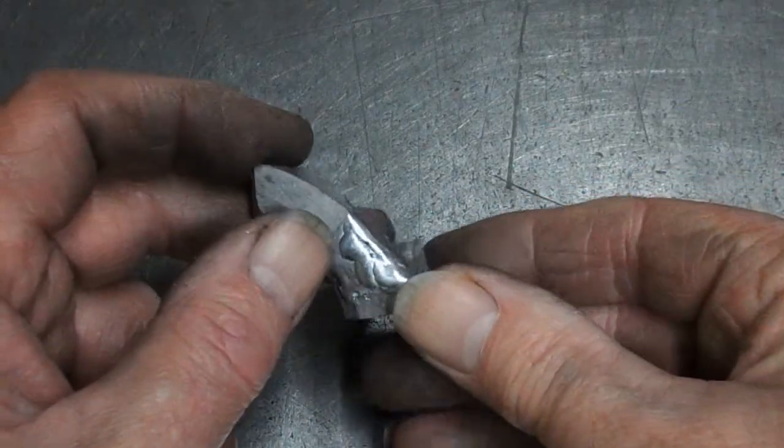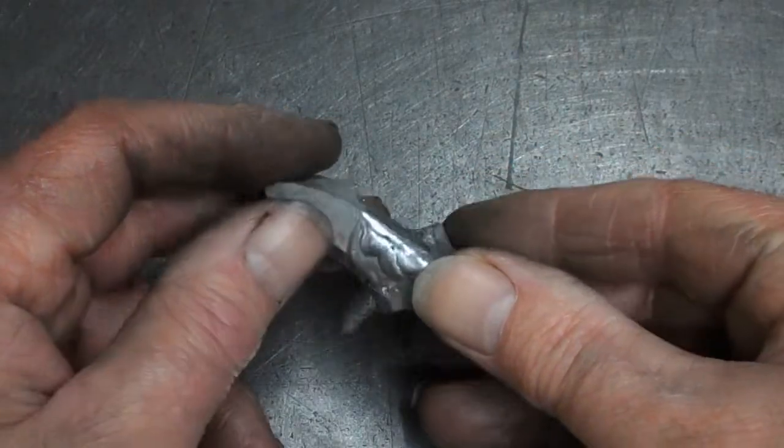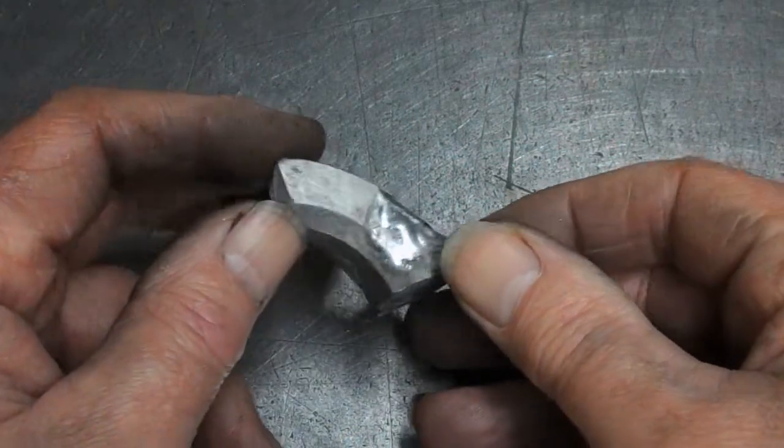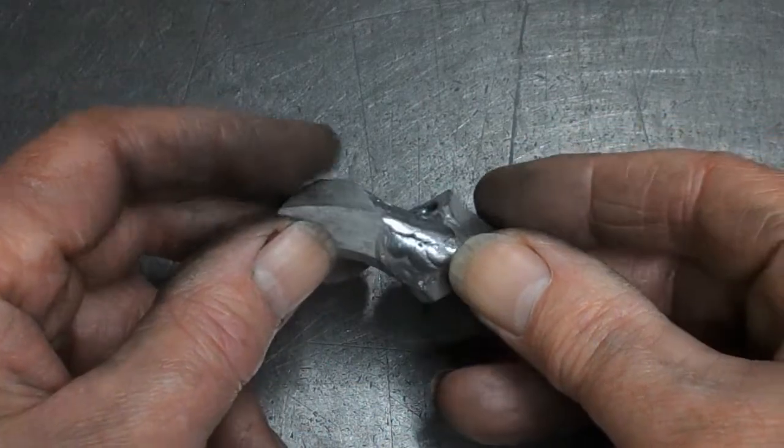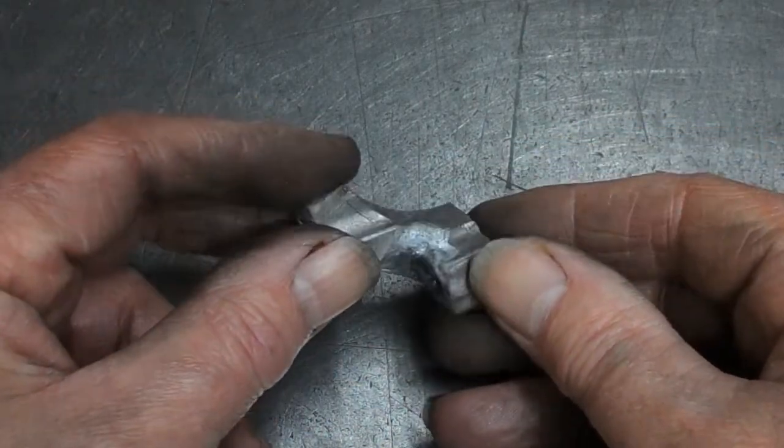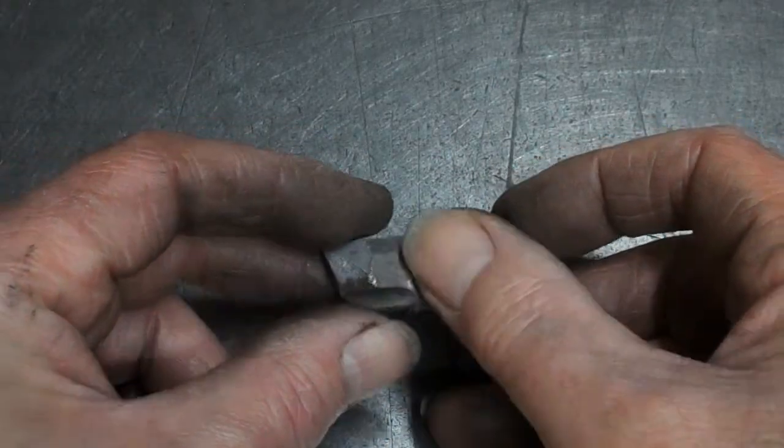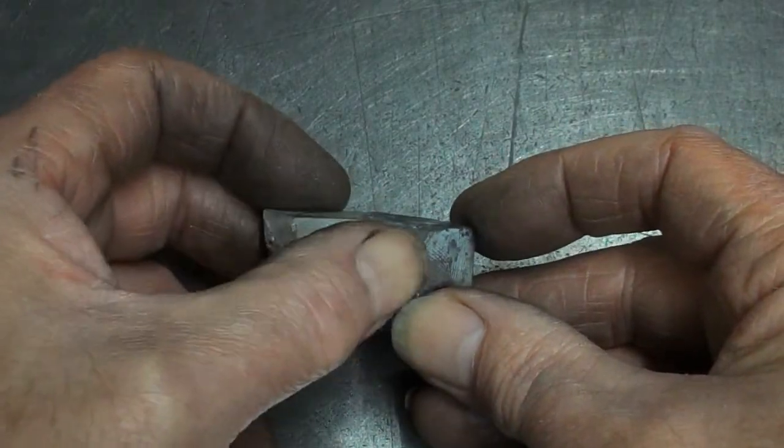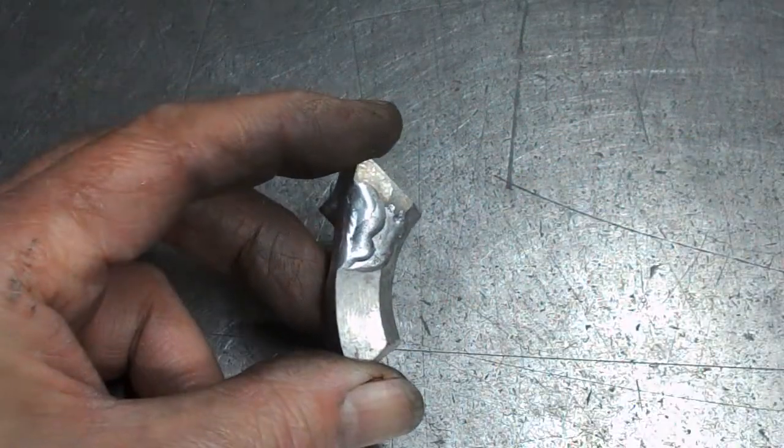Well, crack in this piece all welded up. Once we got going the thing heated up really quick, as you'd kind of expect because it's only fairly small. I think I started off about 70 amps and I was down below 30 by the time I was done. We've got kind of a melt through there, so that's going to have to be filed out. I'm just going to file this blob out and try and smooth this off. I think it might have pulled out a bit.